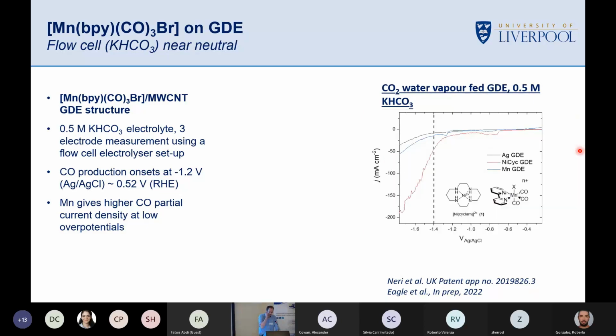What's quite nice is, forget the nickel catalyst for a moment, we're going to come back to that. Here's my silver electrode, here's my manganese electrode, and you can see that we're getting an okay current density. It's not great by any stretch. These are quite low overpotentials though. If you work it out, we're around about 0.5 volts RHE, minus 0.5. Our manganese catalyst seems to be outperforming our silver benchmark, so that's a good sign.